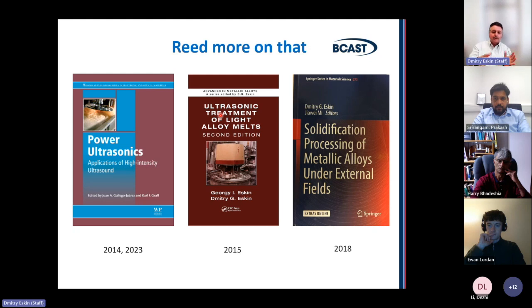Of course, if you switch on ultrasound and leave it there, it will coalesce again and drop to the bottom. If you talk about bismuth, for example, usually immiscible alloys have light and heavy fractions. So there are examples of that. There was a project in BCAST on immiscible alloys a few years ago when they also added titanium boride, I think, for stabilization of droplets. And it was shown that when you do it with cavitation treatment, the result is further enhanced. And we currently try to work in this area.